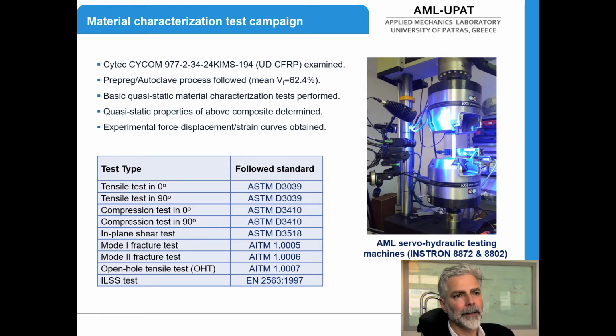As you may see, we perform tensile test in 0 and 90 direction, compression test in 0 and 90 direction, in-plane shear test, and then interlaminar fracture toughness for mode 1 and mode 2, open hole tensile test, and the ILSS test. The mechanical characterization test was made according to the ASTM standards. The interlaminar fracture toughness test was made, and the open hole test was made using the Airbus standard, and the ILSS was made using the EN standard.